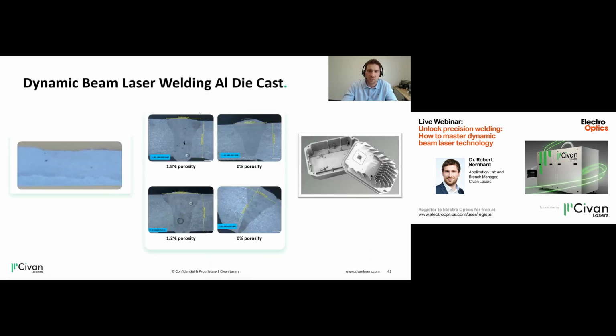We can see this here again. Here I changed the frequency of the shape, and you can see that again, we have the ability of changing and removing porosity while welding. And I'm really happy about these welds where we're able, in this cross section at least, to reduce the porosity to a minimum.